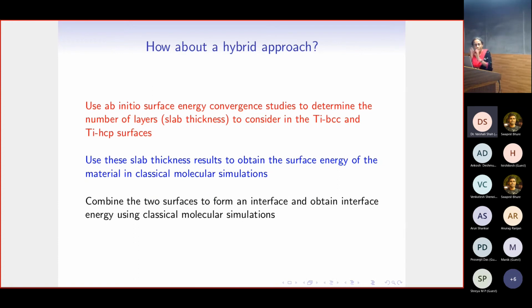Then we thought a little bit and said, how about we follow a hybrid approach? We do the surface energy convergence through ab initio and use this information. So we don't do surface energy convergence by classical simulations at all. We know the number of layers at which our ab initio energies converge, so we simply pick that number and use it as the slab thickness we want to work with in classical simulation. We are going to repeat the calculation for surface energies for these thicknesses, even though the surface energy numbers don't match, and we'll see what happens.